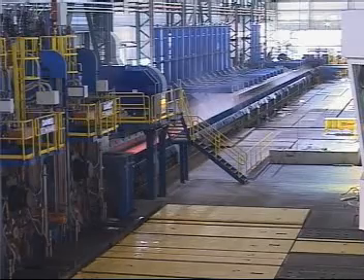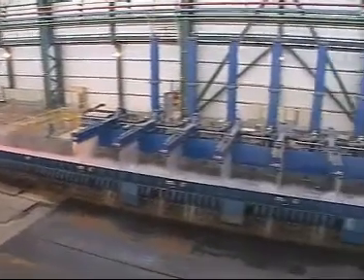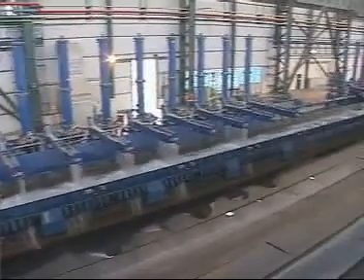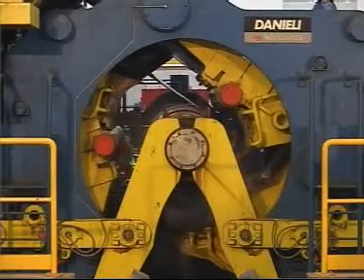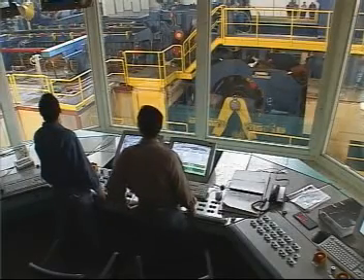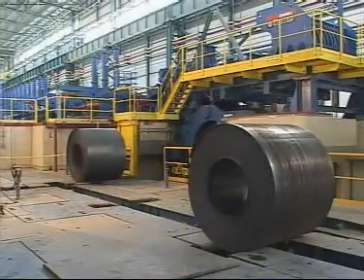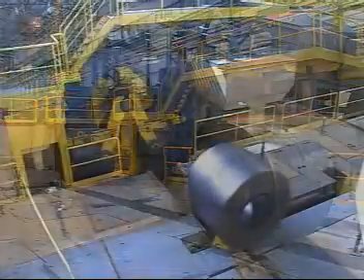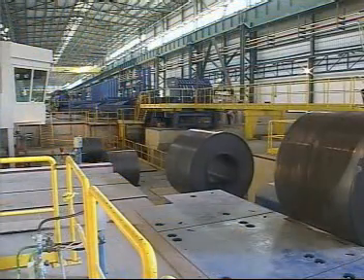Semi-endless rolling of ultra-thin gauges will be possible with the installation of a very short run-out table and an intensive strip cooling system after the last finishing stand, a high-speed drum shear to separate the long slab rolled in semi-endless mode into individual coils with a maximum exit speed of up to 20 meters per second, and a carousel coiler placed very close to the last finishing stand.